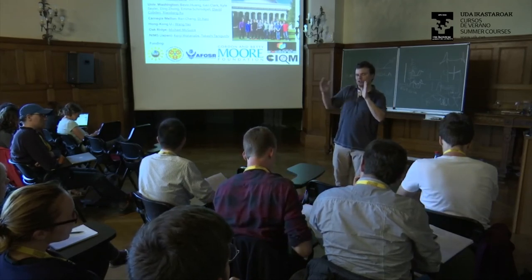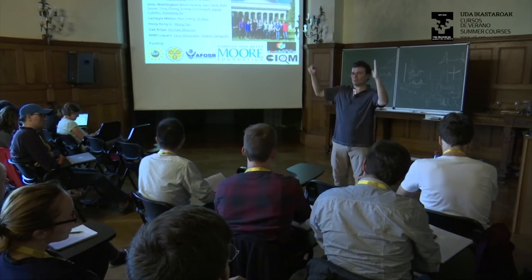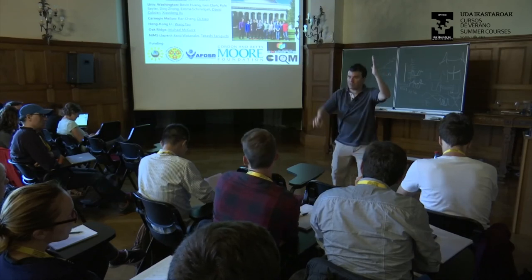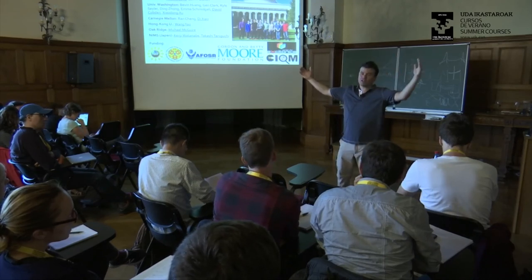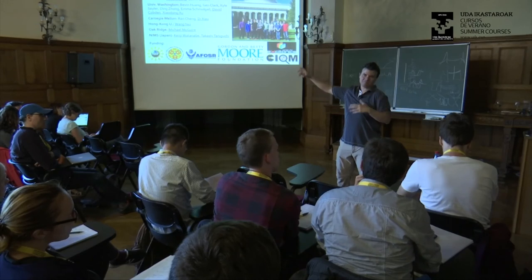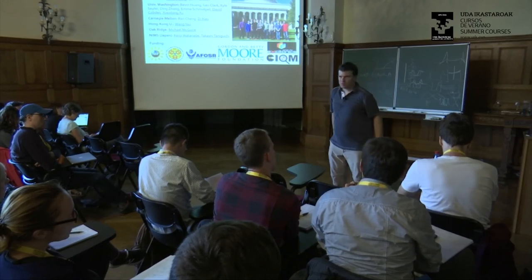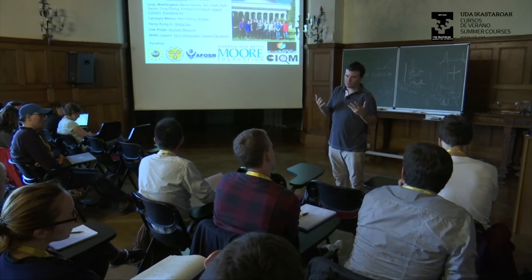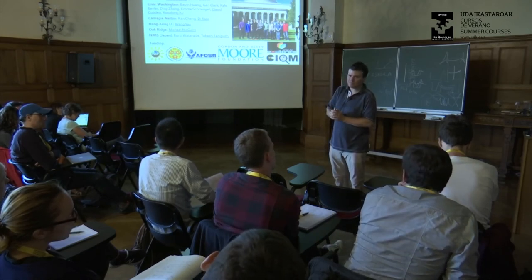So for some of the data where I show length dependence, it could be that the length was in reality not 300 nanometers as I thought, but a micron and then back, so much longer effectively. And that's why the resistance increases. So this is a materials issue. We have to be more careful with exfoliation and try to make better devices.